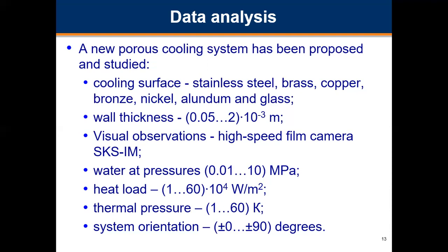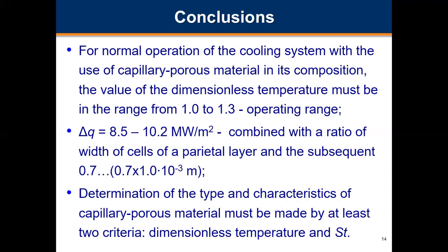Visual observations allow to describe the physical picture of the process and summarize the experimental data on the internal characteristics and heat fluxes with an accuracy of plus minus 20%, depending on the thermophysical properties of the liquid, wall temperature, pressure, excess liquid, type of porous structure, and heat exchange surface. Depending on the ratio of maximum value of the wall temperature and the temperature of the working fluid on the saturation line, the priority may be a particular capillary porous material.